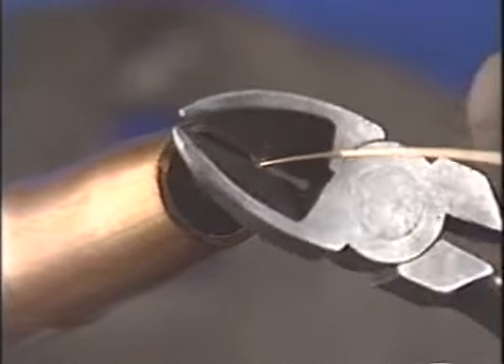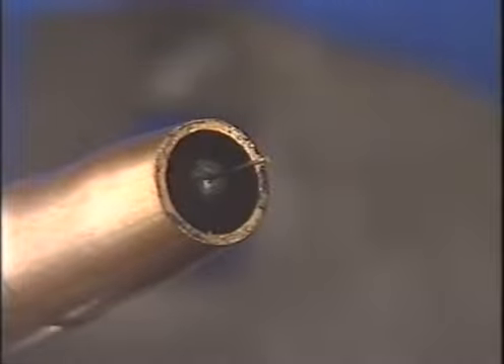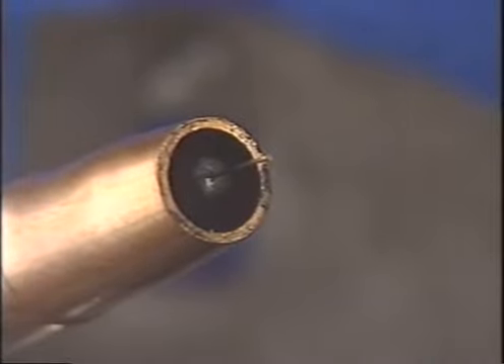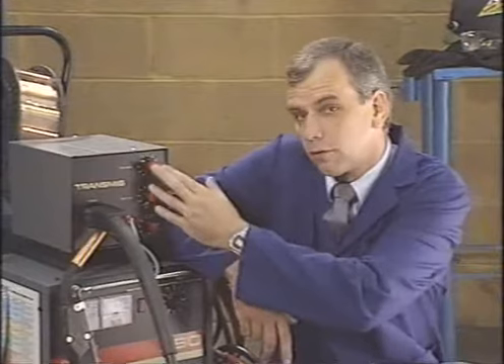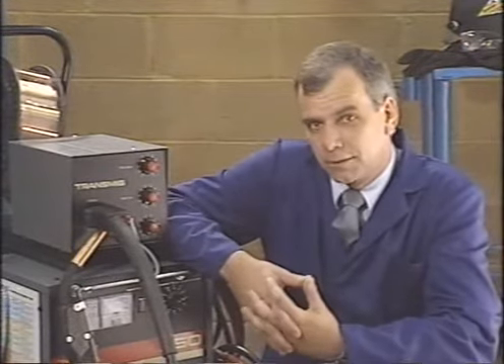Trim the excess electrode wire to a distance of 10 millimetres from the contact tip. When welding, the stick-out length will then adjust depending on the wire feed setting. It is important to remember that the longer the stick-out length, the less arc energy occurs. At this point, welding can commence. Now, keep in mind that fine-tuning of the controls may be required to optimise the welding process.